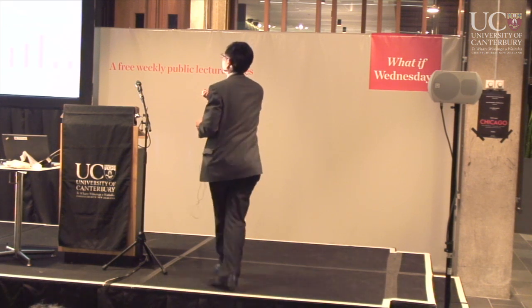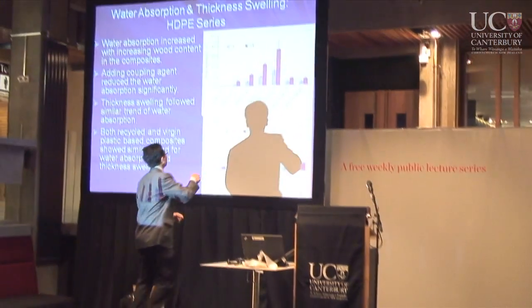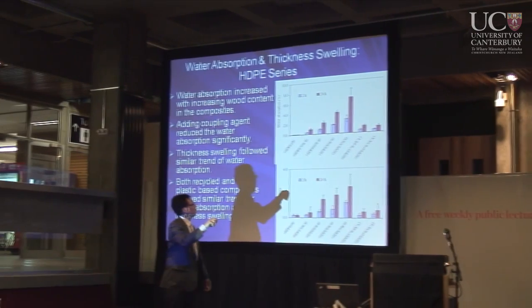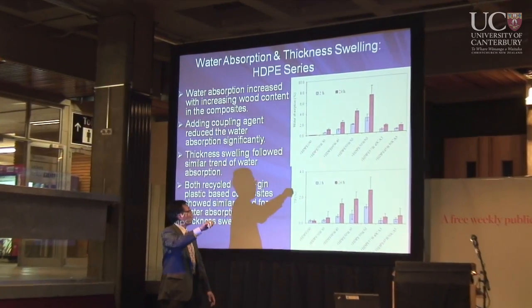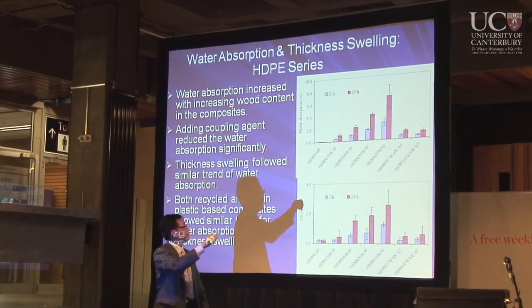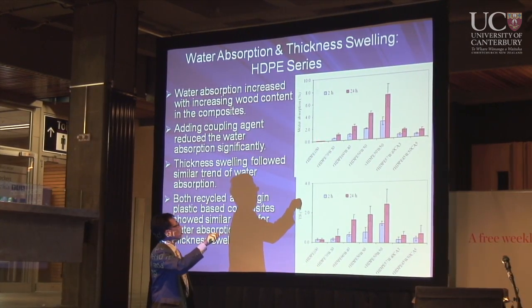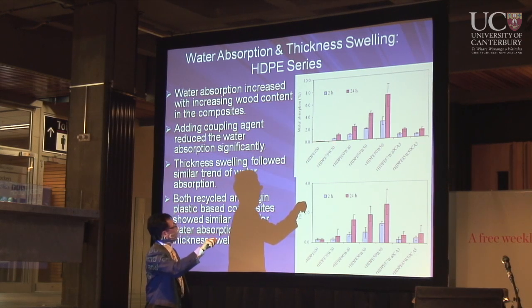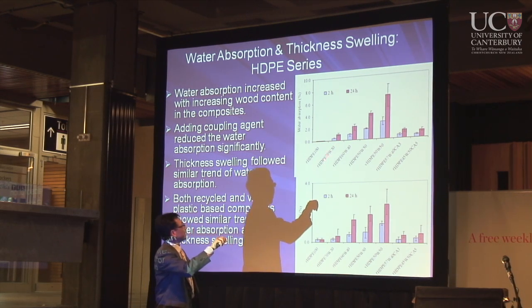This is putting the sample in the water. You can see the result here for 2 hours and 24 hours. So this is 100% plastic. No surprise, almost nothing. No water is absorbed. And this is 70% plastic and 30% wood, and this absorbs some water.